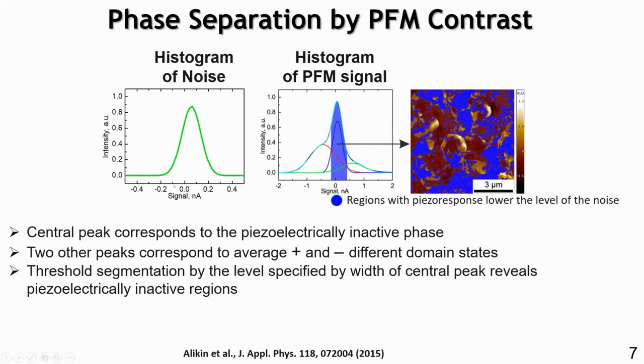And if we also measure the noise level of the system, we can use a threshold, the half width of the peak, to separate the regions without piezoelectrically active material. If we talk about BFO, single phase BFO is piezoelectrically active, and all the secondary phases are piezoelectrically inactive. So in that case, if we have the statistics of such a scan across the surface, we can measure quantitatively the area of piezoelectrically active and piezoelectrically inactive phase. And from this comparison, we can calculate the percentage of piezoelectrically active and inactive phases.